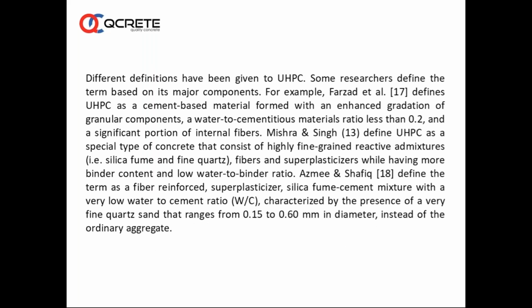Different definitions have been given to UHPC. Some researchers define the term based on its major components. For example, Farzad defines UHPC as a cement-based material formed with an enhanced gradation of granular components, a water to cementitious materials ratio of less than 0.2, and a significant portion of internal fibers. Mishra & Singh defined UHPC as a special type of concrete that consists of highly fine-grained reactive admixtures, silica fume and fine quartz, fibers, and superplasticizer, while having more binder content and low water binder ratio. Azmee & Shafiq defined the term as a fiber reinforced superplasticizer silica fume cement mixture with a very low water to cement ratio, characterized by the presence of very fine quartz sand that ranges from 0.15 to 0.6 mm in diameter instead of ordinary aggregate. So the definitions are different